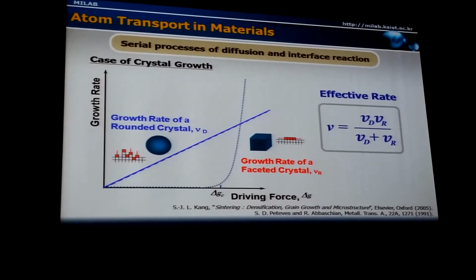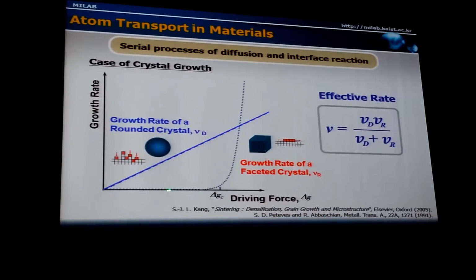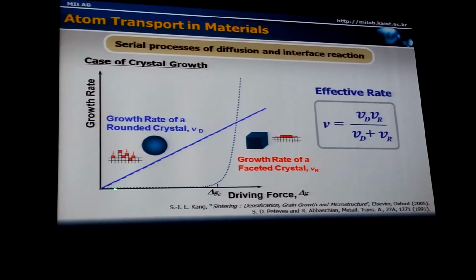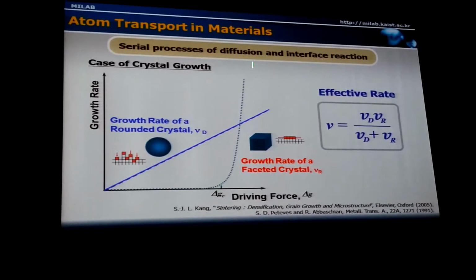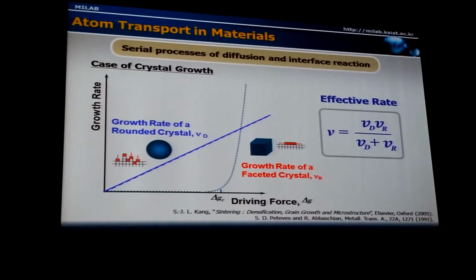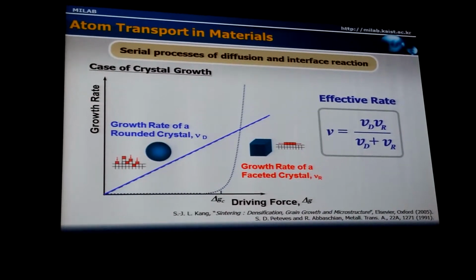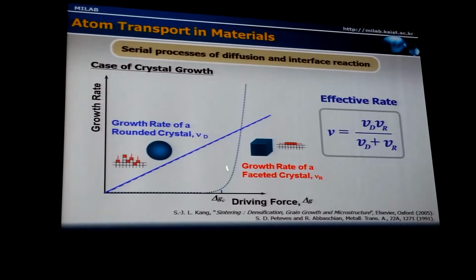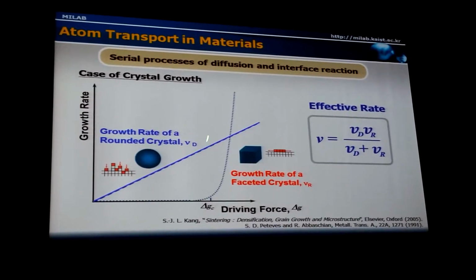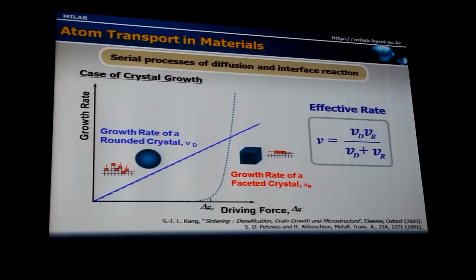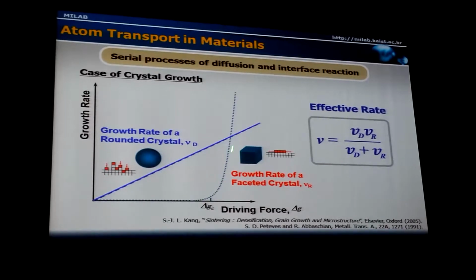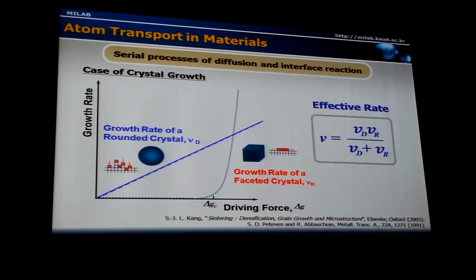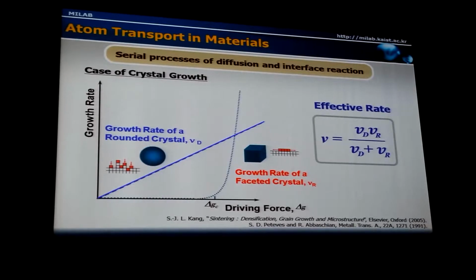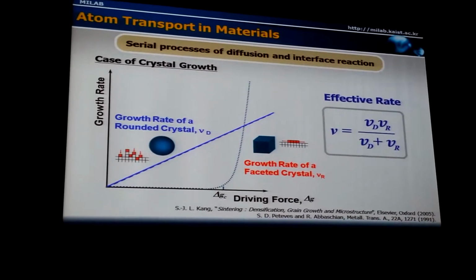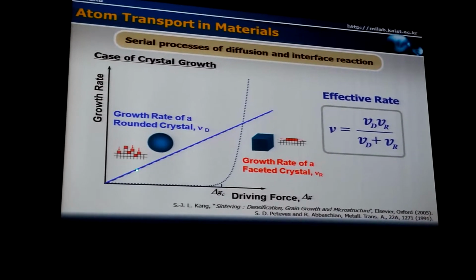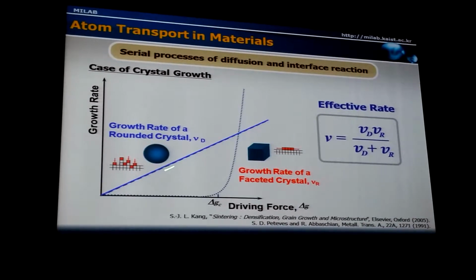On the other hand, in the case of a faceted crystal, interface reaction is predicted to be a certain function of the driving force. So, for example, in the case of two-dimensional nucleation and growth, the growth rate is an exponential function of the driving force, as this dotted curve shows schematically. But the diffusion rate through the liquid matrix is not affected by the shape of the grains. Therefore, the diffusion rate is expressed by this straight line.